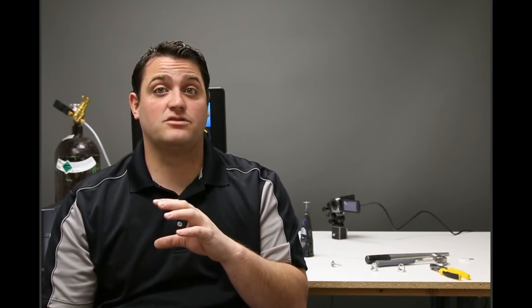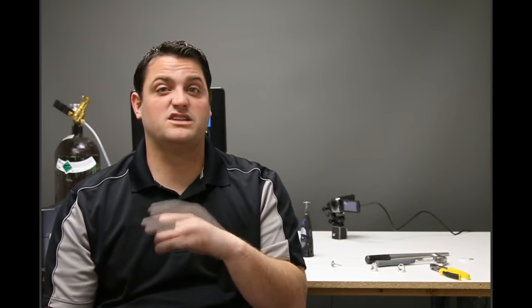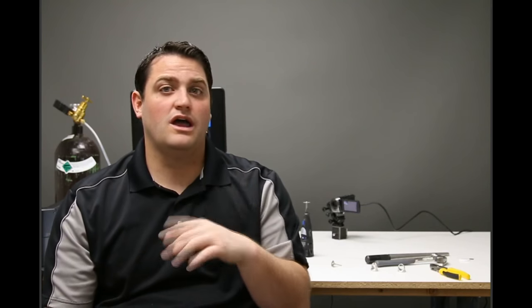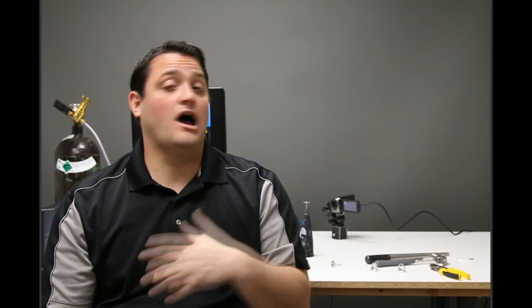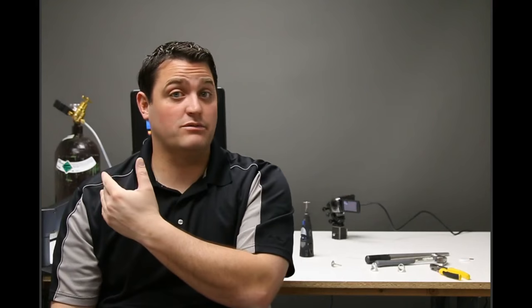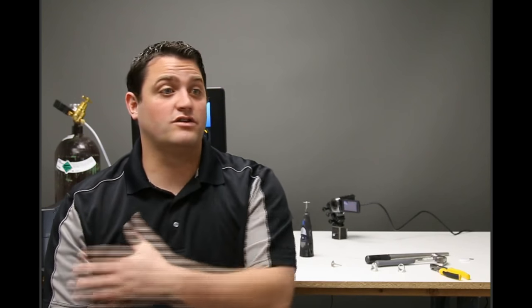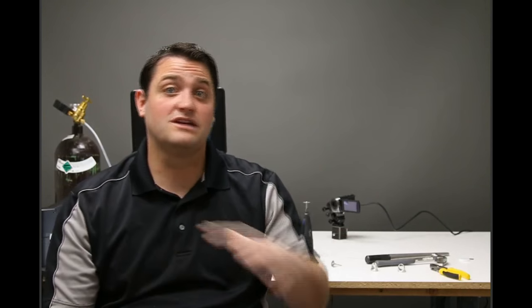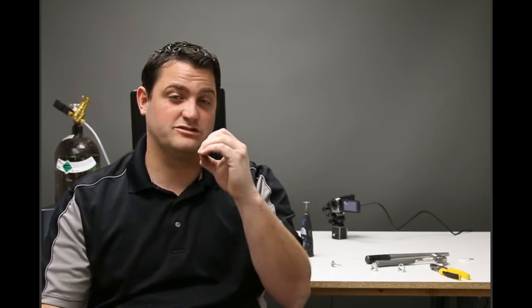They don't want to add a tremendous amount of heat, and they want to be very, very careful and very, very slow at heating the piece up. Other jewelers like to hit it with tons of power, like I was hitting it with 30 plus up to 50 trying to smooth it out, and that's okay. It just depends on the technique. Some people believe that heats the metal too hot and you crystallize it. Other jewelers believe that if you're working too small, then you're not getting enough melt to flow together and you're getting those pockets on the inside. So it really just depends on your trial and error. Everybody does it a little bit different.